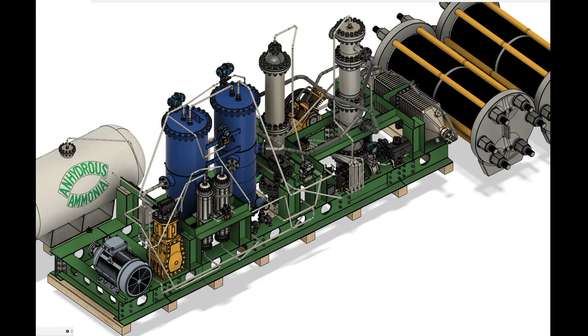Since we know decomposition favors low pressure and high temperature, we can assume low temperature synthesis would be ideal. But the reality is the reaction is extremely slow at low temperatures, despite theoretical yields being very high, so designers were forced to increase temperature to speed up the kinetics, but once this is done, a precarious situation is reached. If pressure is lowered, a dramatic loss of activity is experienced, as we are now essentially decomposing the freshly formed ammonia, reaching a zero-sum process, where decomposition outstrips synthesis.